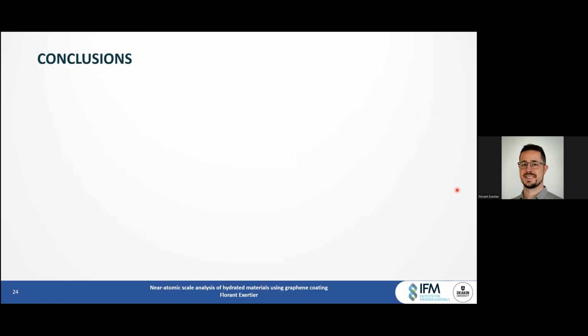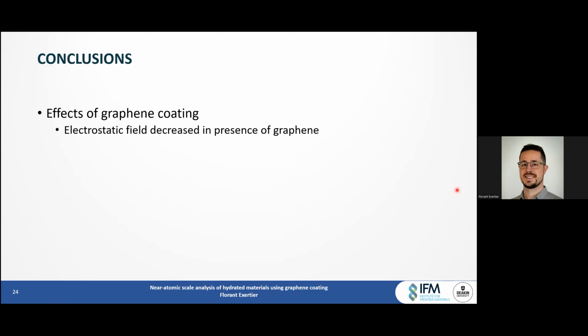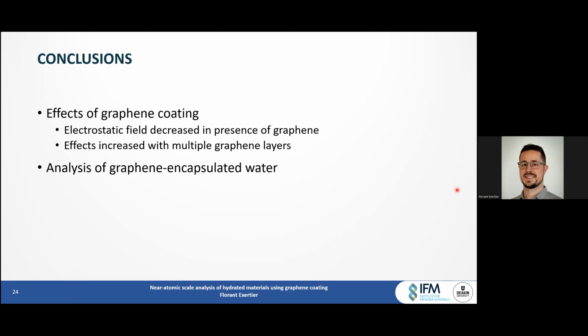And now to conclude, so this study was separated in 3 axes, and the first one was trying to understand the effects of graphene coating on an atom probe specimen. And we realized that the electrostatic field was decreased in the presence of graphene, and the effects were increased with multiple graphene layers. Then we had a look at water that was graphene encapsulated on top of sharpened tips.